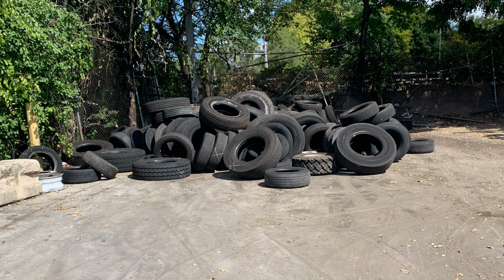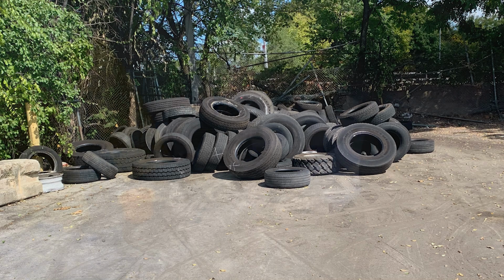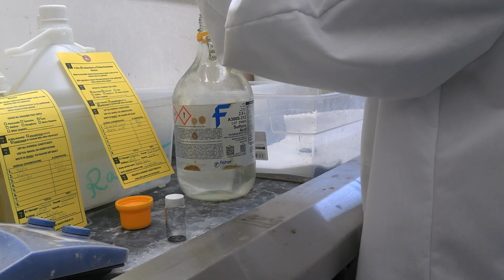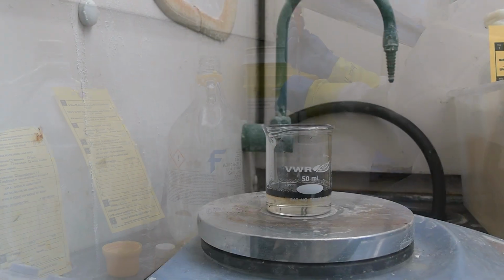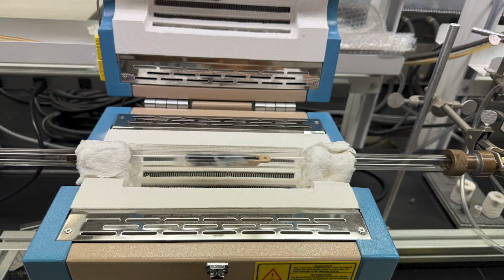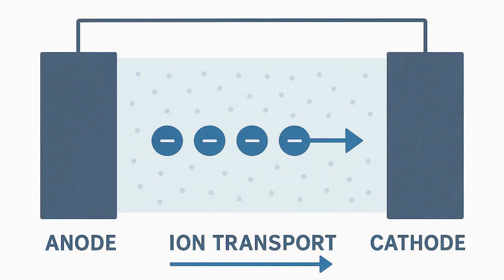How do we go from an elastomer, an amorphous polymer, to a conductive material that shows crystallinity and structure? First, we etch the material by putting it in an acid bath, which will create defects in the structure. Then, we move to the tube furnace, an oxygen-free environment, where our tire material, which has a disordered atomic structure, slowly becomes more ordered, producing conductive hard carbon. Remember when we created those defects? Those defects are now pores that will allow for ion transport into and out of the structure.